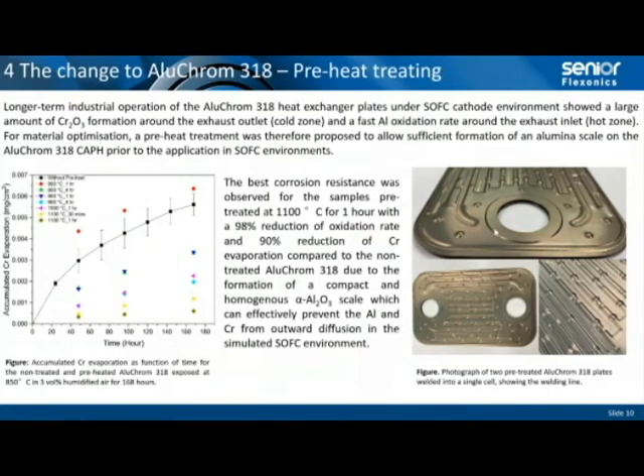So just to finish off what Kun was saying, Kun proved that he could form an alpha alumina layer at 1100 degrees C in an hour, and that was done on a single plate. Then the concern for Senior was, with that alumina layer, would it cause us problems with our laser welding? So we did trials of laser welding the plates together to see what the effects were, and the results were very positive.